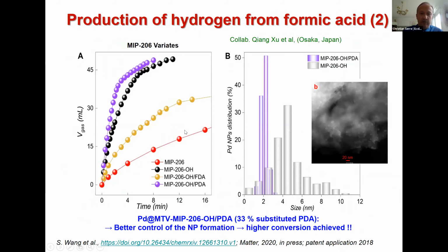But one of the main interests of this type of mesoporous solid is the possibility to change the functional group. So here we decided to make variants of the MOF by introducing either furan dicarboxylic acid or pyrazole dicarboxylic acid. And pyrazole is known to bind strongly palladium. If you compare the pure MOF with the OH group, the particle size distribution of palladium particles is above, let's say, 4 to 5 nanometer, which is larger than the pore size of the MOF, which means that the particles are at the outer surface of the MOF or located within defects.